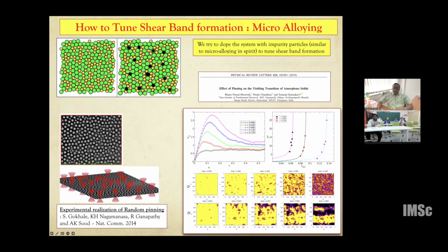And when we looked at the spatial map of plasticity, we see that when you do not have any pin particles, you get a clear shear band type behavior, as in the lower panel data set of maps. But when you have some amount of pinning in the system, then you get homogeneous yielding. This is signified by this stress peak, which is broad.